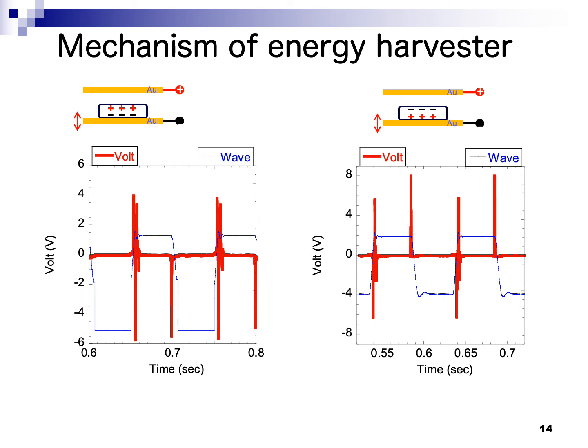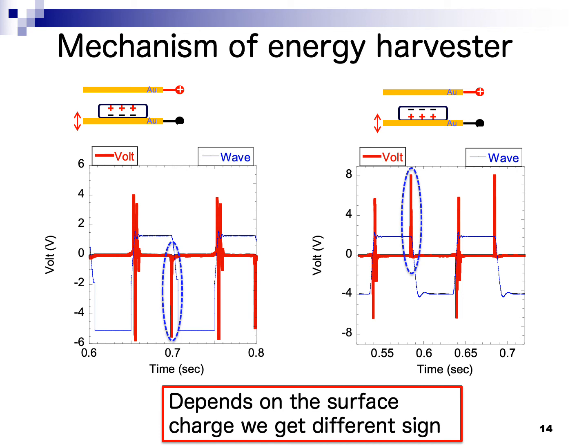And the blue line is the position of the electrode. And here, the electrode is attached to the electret. So, for example, when the electrode detaches from the electret on this positive charge side, it gives a negative current. However, if it is the anion side, then it gives a positive sign. So if we flip it, it gives a different sign. This is one proof that depending on the surface charge, we get a different sign.